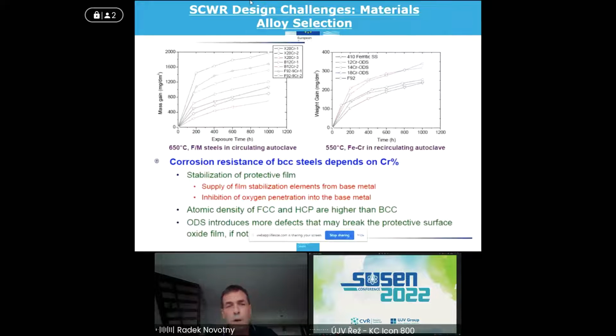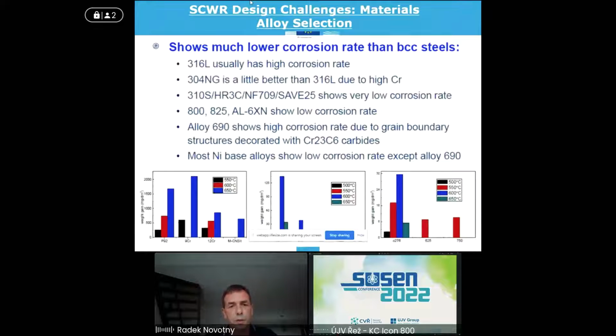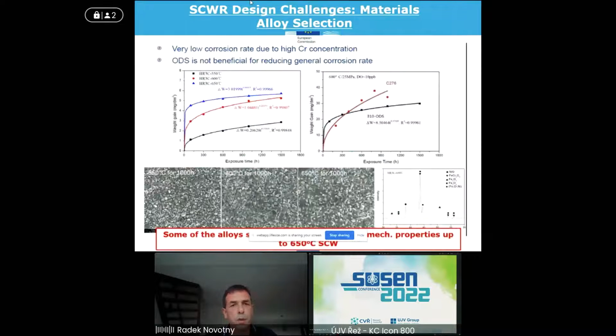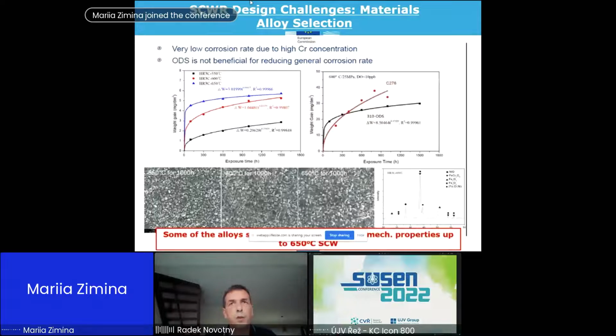But when we compare different results from different labs, we realize how big the differences are and how much we must work on improving the inter-relation of these labs. Anyway, austenitic stainless steel is much better. There are many steels which show very good corrosion resistance even in high temperature supercritical water. I would show one example, which is the alloy HR3C, the Chinese equivalent of 310 stainless steel, which shows very low corrosion rate because of the high chromium content. Again, the research also focuses on ODS because of their potential for good mechanical properties, but at the moment it doesn't show a very big benefit in terms of corrosion rate.